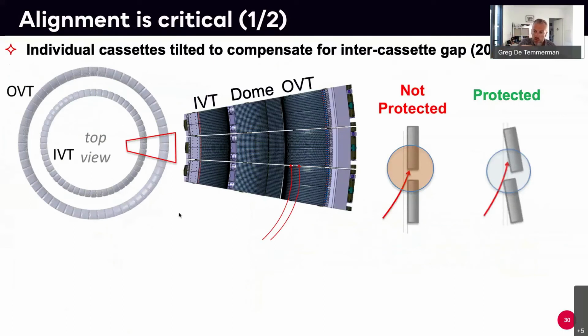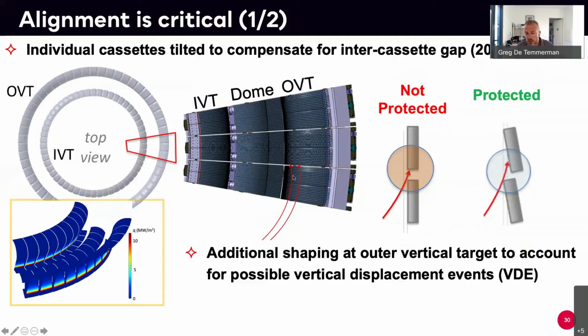What we want to avoid, so the plasma is flowing along the magnetic field lines, what we want to avoid is that because we have finite components, we have gaps in between. So you can have misalignment between the different components. And we want to avoid that a field line can actually penetrate and see an edge and not glide on a smooth surface. If you do that, basically you have all of the plasma power on a very tiny area at normal incidence, and you would melt basically anything you have. So you have to make sure you hide all of those edges by actually tilting the different components. So each of those cassettes is actually tilted by a degree or so compared to its neighbor, because then you create a natural protection. So alignment is extremely critical.